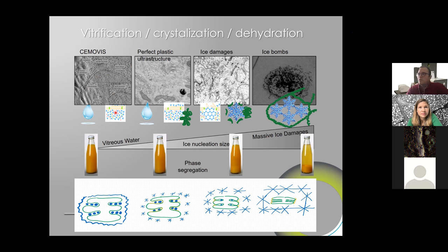When the water starts to crystallize, one of the big questions is that the ice crystals start to grow and push away the material which is inside. The second point is the crystal tends to like being as pure as possible, so it will extract the water from the molecules surrounding it so that it can grow. And by doing that, it progressively dehydrates the proteins which are around,